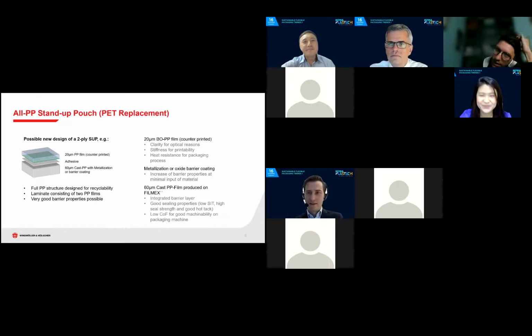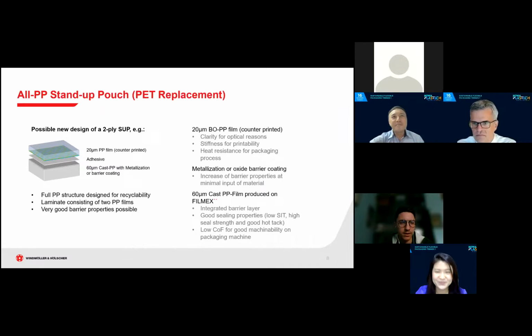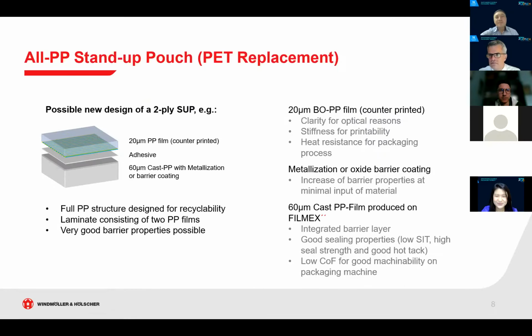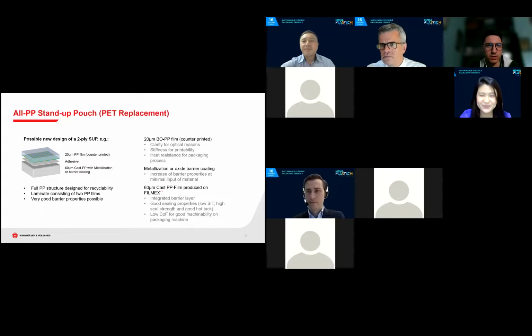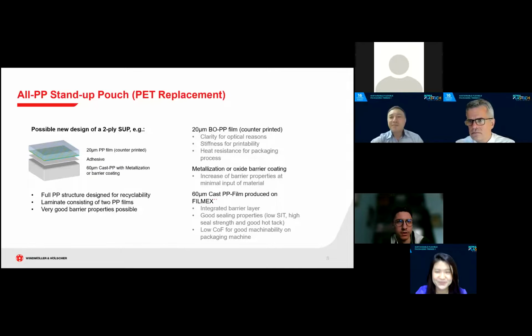Yeah, basically right now it was not really possible to achieve the transparency on the blown film lines or something like that. But now we have started producing MDOP on the cast lines, and what we found out when we started is that honestly the level of transparency was not the one that you can achieve in blown. Then also with the help of ExxonMobil, Dow, and so on, the producers of the raw material, we found out the right direction to follow, let me say. And now we have a sample of film that has very, very good transparency, and so printable, and all the things that you thought were not possible, now let me say that are possible.